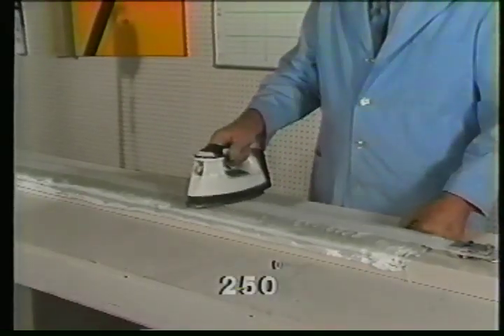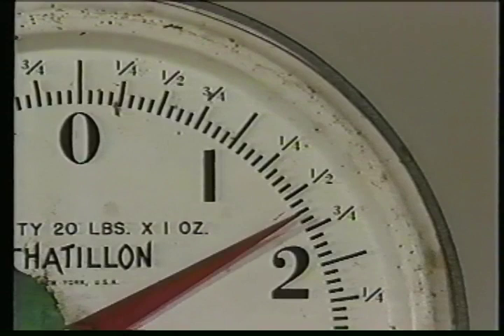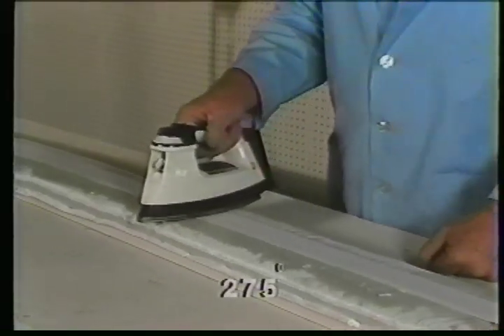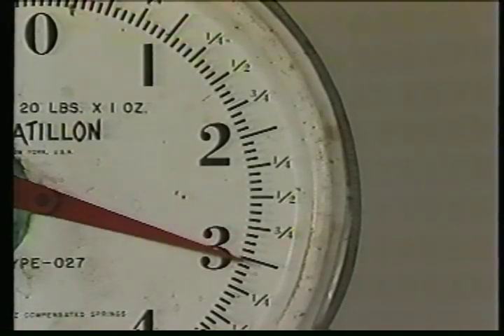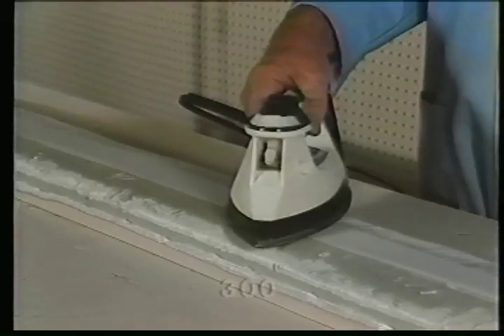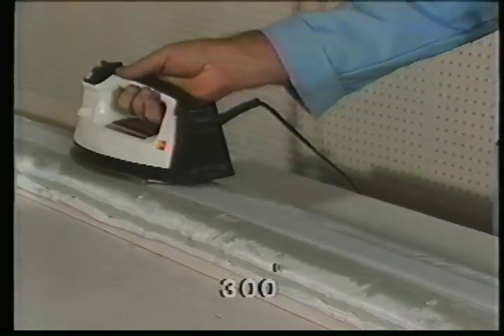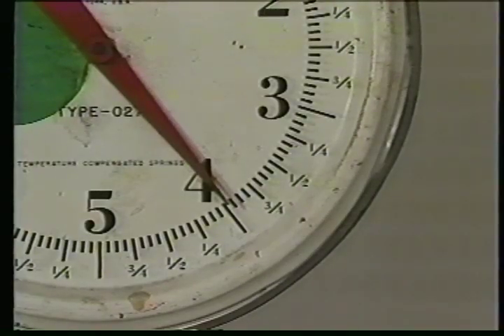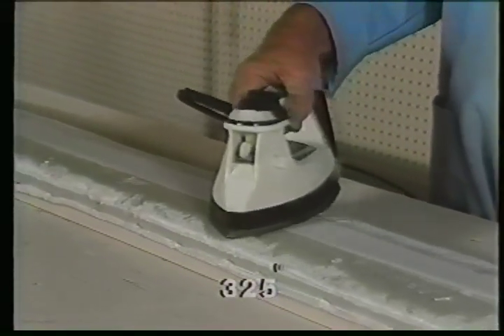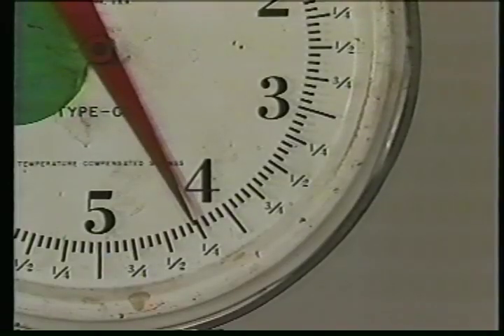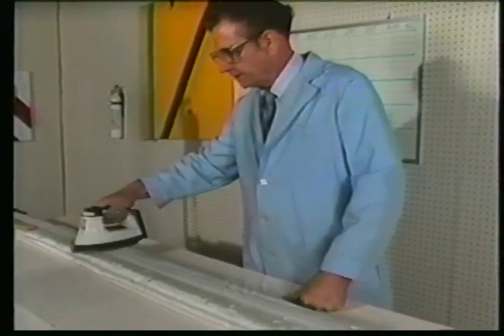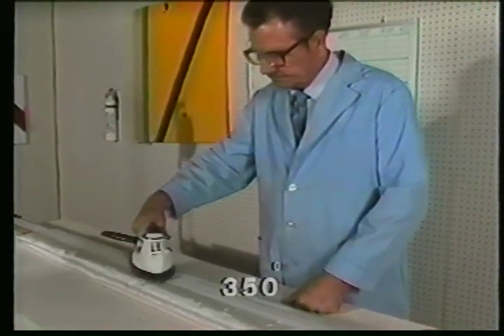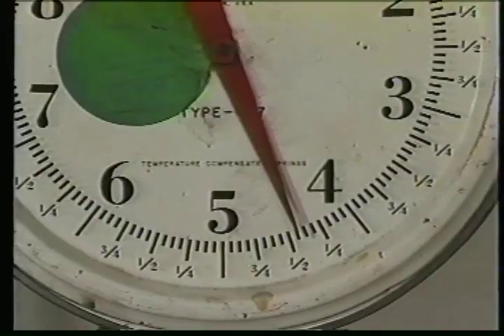At 250 degrees, the tension increases to 1 pound 10 ounces. At 275 degrees, the tension is 3 pounds 4 ounces. At 300 degrees, the tension is 4 pounds. At 325 degrees, the tension is 4 pounds 5 ounces. At 350 degrees, the tension is 4 pounds 7 ounces, which is almost 2¼ pounds per inch width.